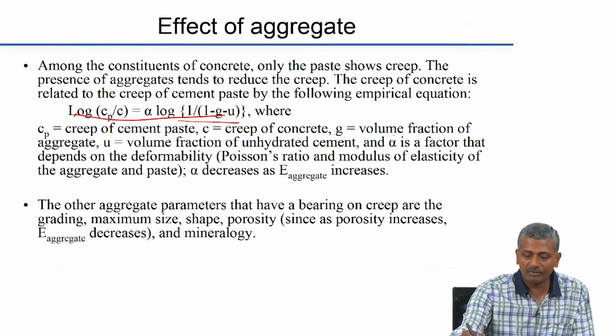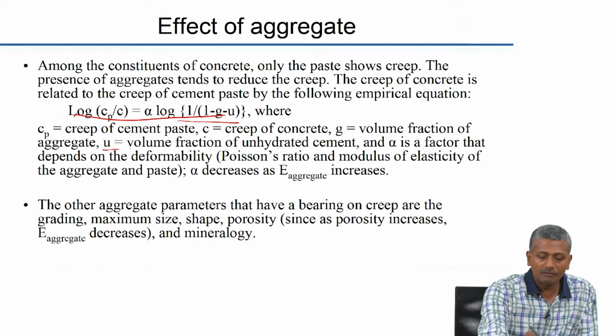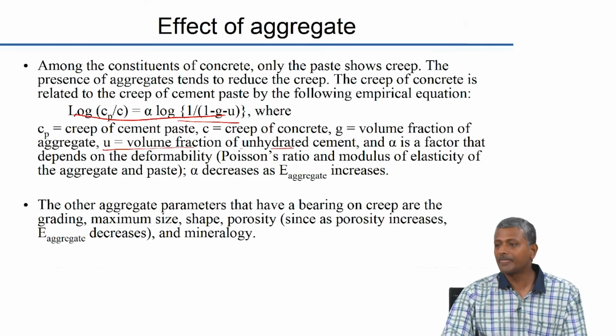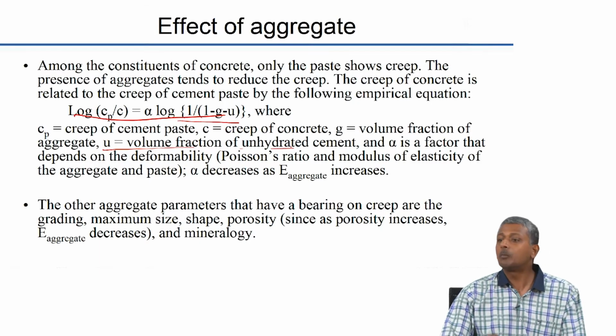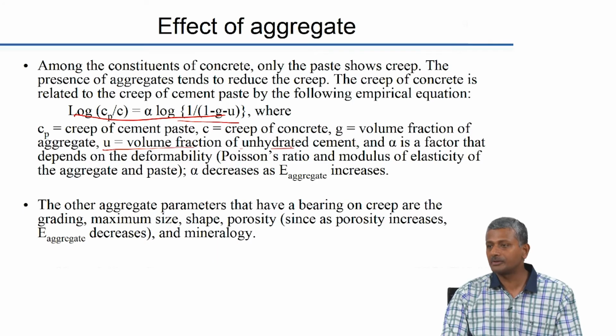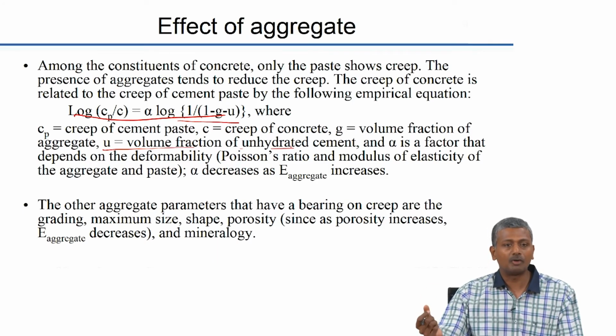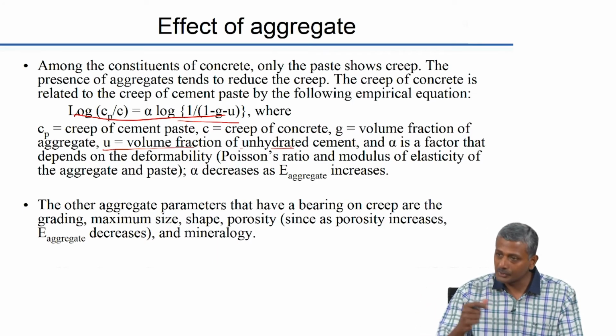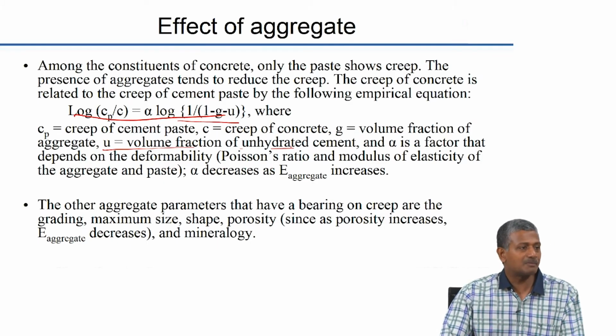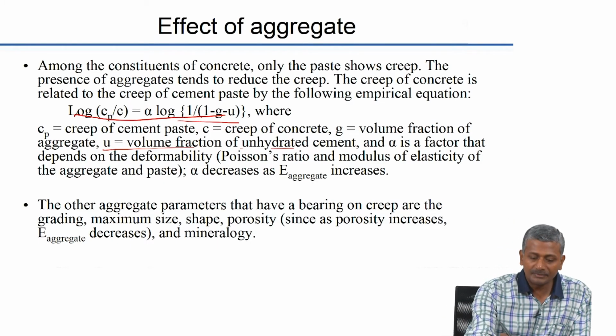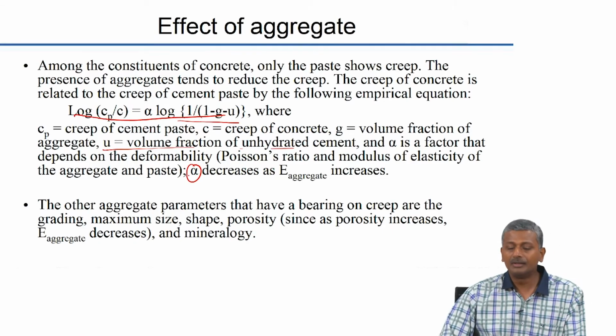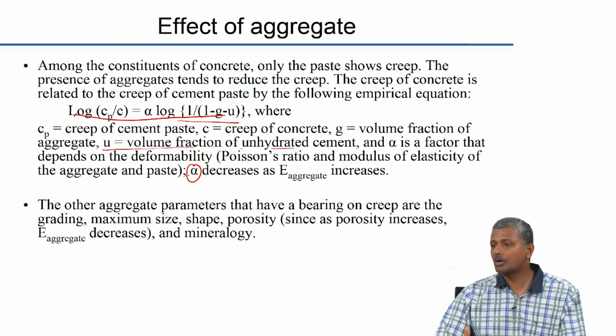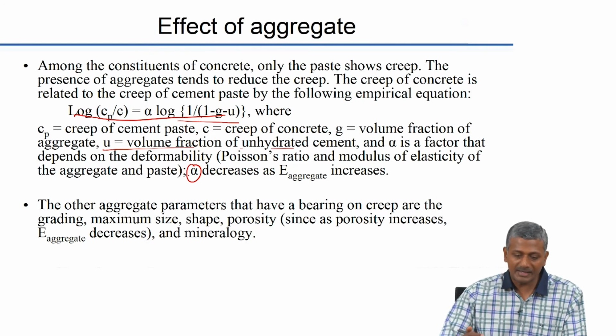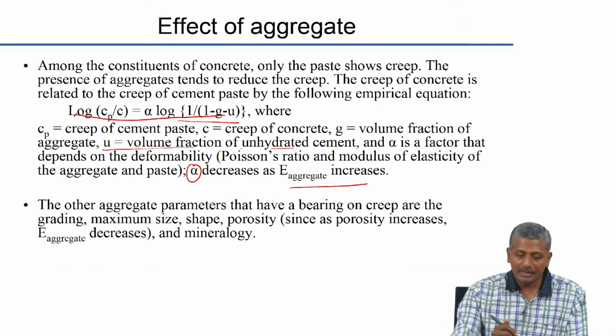So, here G is the volume fraction of aggregate and U is the volume fraction of unhydrated cement. Please remember that not all of the cement hydrates. The unhydrated cement actually will work positively when it comes to volumetric deformation, because this is a component that is not going to deform, being extremely stiff, as opposed to the hydrated products which do not have the same level of stiffness. So, this alpha is basically a constant or a factor which depends on the deformability of the material. Again, deformability depends on the modulus of elasticity or stiffness of your material. So, as aggregate modulus increases, alpha decreases.